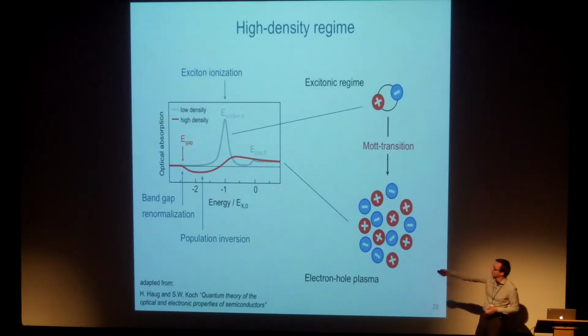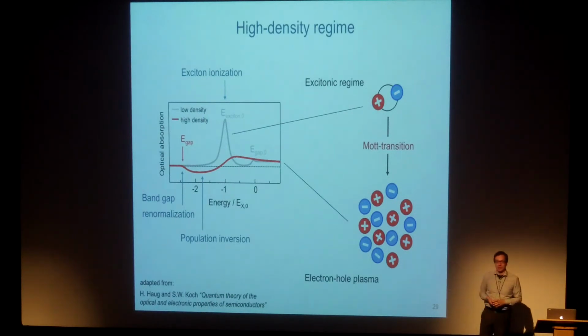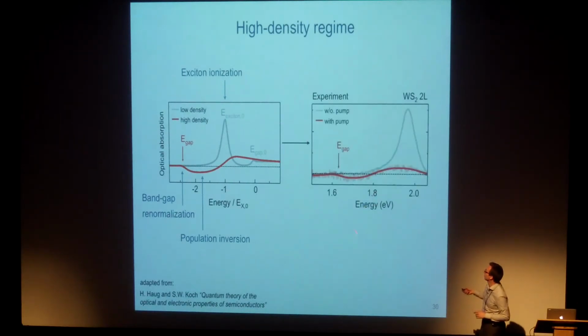So roughly over this region, we will have electrons populating the conduction band and holes the valence band with very high probability. And in the absence of all other absorption and scattering channels, that would be the regime where one could build a laser and we will have gain and amplification. And this is basically what we observed in the experiment, very close to these predictions.